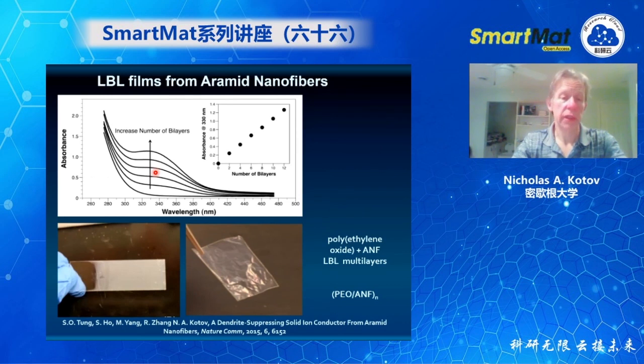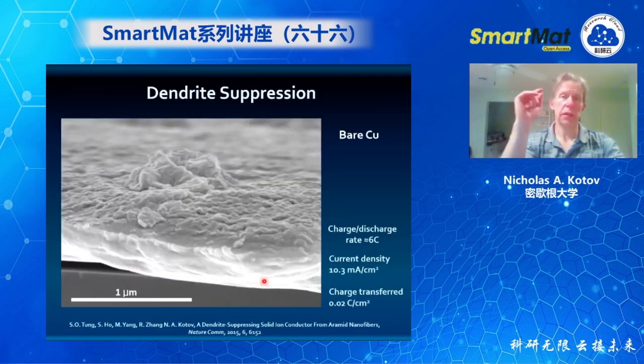These materials can be used in a variety of technologies. I would like to show you some of our results for energy, for batteries. And the first data were obtained by aramid nanofibers made by our favorite technique, LBL. And we learned that these stiff, conformal, insulating, ion transporting layers can actually prevent the growth of very stiff metallic dendrites. Not only lithium, which is fairly soft, but also copper and zinc.